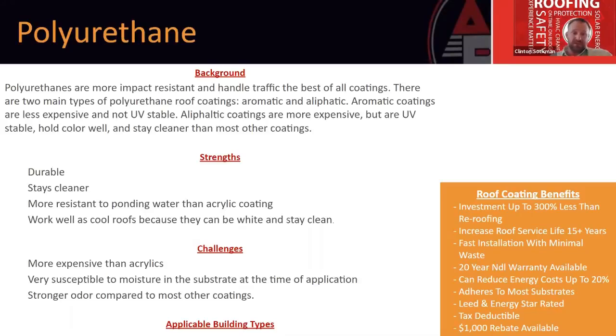Some of the downsides to your polyurethanes: high initial investment costs, susceptible to moisture in the substrate at the time of application. These coatings need to cure fully, and they're so good at holding moisture in top and bottom that if there is trapped moisture at all, when that substrate tries to heat up, if it's not fully cured, the gases will actually push through and cause pinholes in the polyurethane itself. So they can be very temperamental to the application time and the humidity in the air and in the system itself. And then they do have stronger odor.